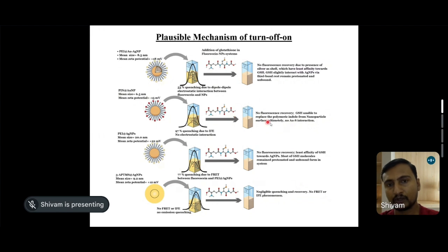addition of glutathione, no fluorescence recovery happened because the polyindole molecules were very strongly adhered to the nanoparticle surface, and glutathione does not get any access to interact with the gold nanoparticle surface. So there was no chance for the gold and sulfur interaction. Similarly, PI, as I discussed, quenched, but no recovery after the addition of glutathione, because of the least affinity of thiol group for AgNP, and 3-APTMS stabilized silver nanoparticles are not very well quenched.